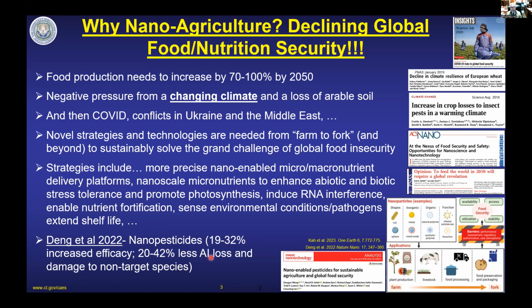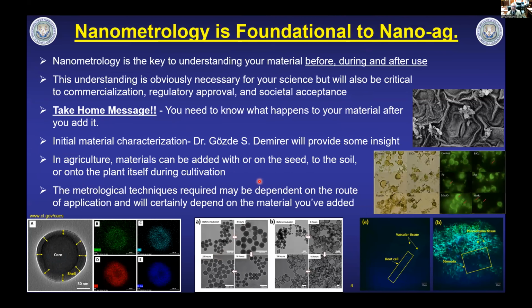So, coming with that is the precision that we talked about. And these numbers involve no optimization. For example, we were working on commercial copper oxide nanoparticles and demonstrating significant increases in nutrition relative to conventional copper. But then we took that commercial copper and tuned the chemistry, changed the composition, changed the morphology. In doing that, we increased our efficacy by an order of magnitude. So I think the increases here can be significant.